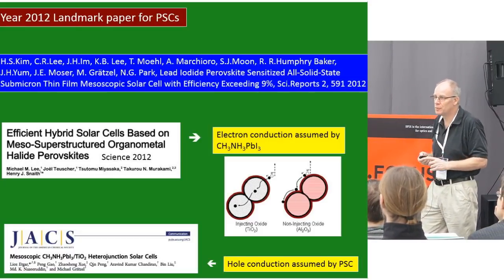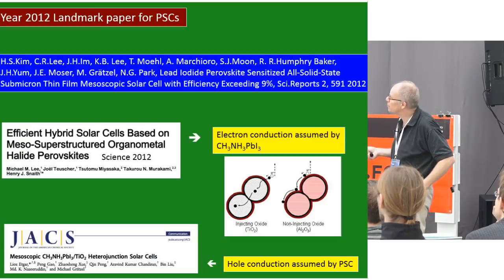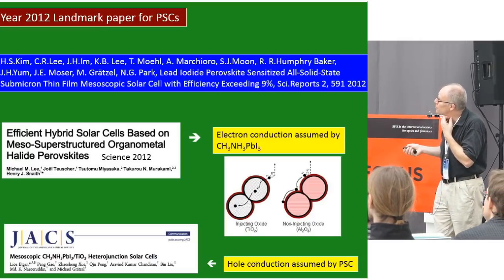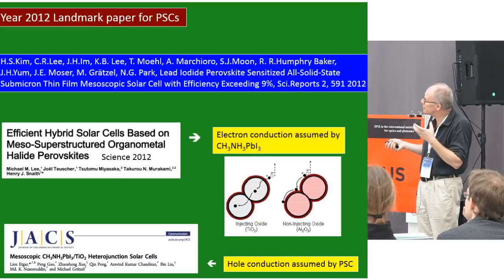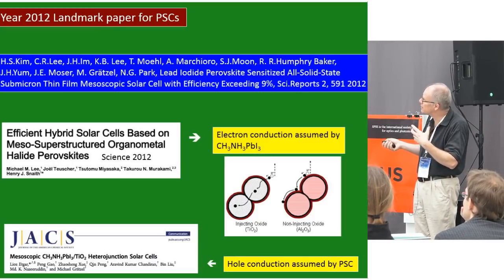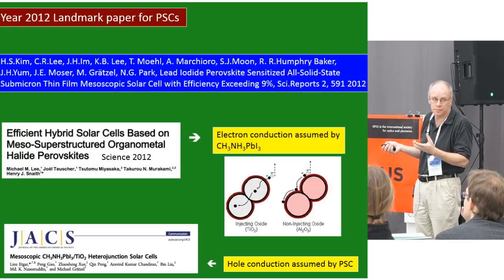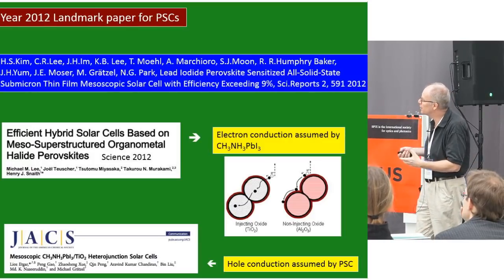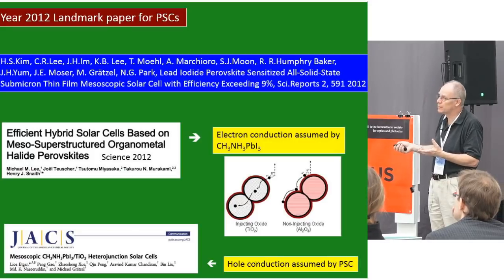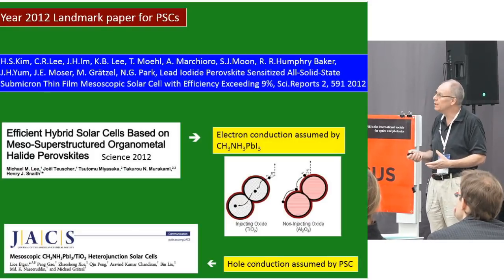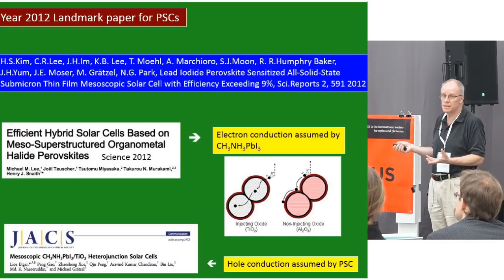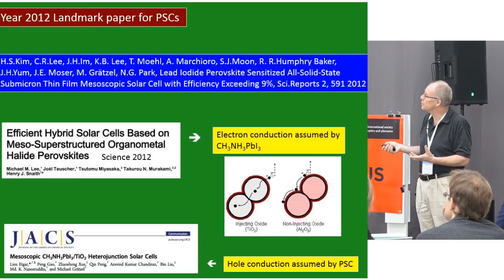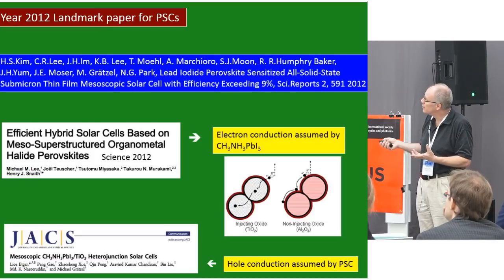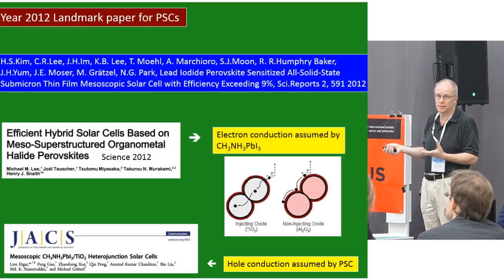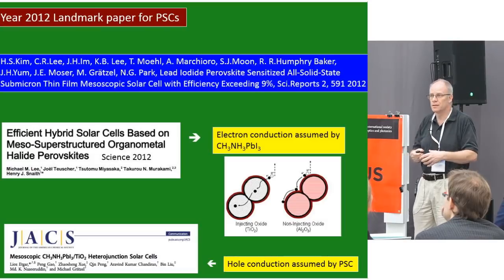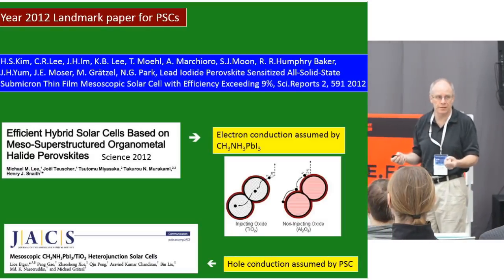But then there was one thing more, which is the key thing in Henry Snaith's paper. He showed that you don't need to use injection. The classical idea from the dye-sensitized cell is that you excite the absorber, and the electron goes into TiO2. He made a blank experiment, a reference, using aluminum oxide instead, which is an insulator and cannot inject. And he could show that the solar cell still works with the perovskite. So that means that the electron transport must be through the perovskite layer to the contact, not into the aluminum oxide. So the perovskite itself can transport electrons.